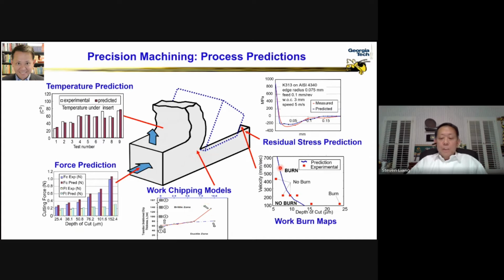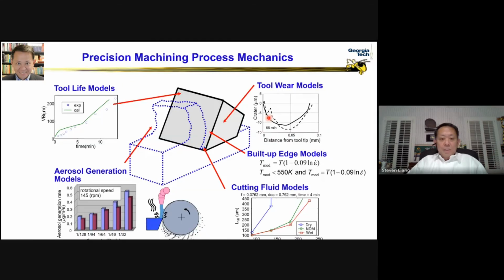And we also worked out a process map to show exactly which range of the depth of cut and velocity process parameters the workpiece will be burned, and also show where the areas of operation are that the material will be just fine. And we also look at the prediction of residual stress out of machining. We'll talk about residual stress in just a minute, if I still have time.